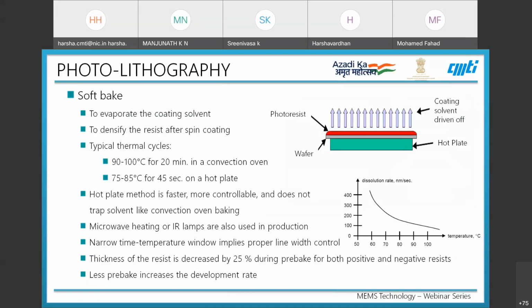So why is soft bake necessary? In order to evaporate the coating solvent and to increase the density of the resist after spin coating, the soft bake step is necessary in the photoresist coating process.